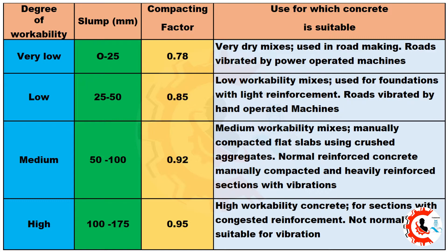Two: low slump, 25–50 mm. Compacting factor = 0.85. Low workability mixes used for foundations with light reinforcement, and roads vibrated by hand-operated machines.